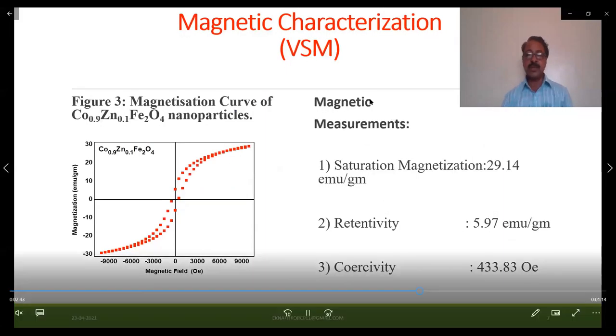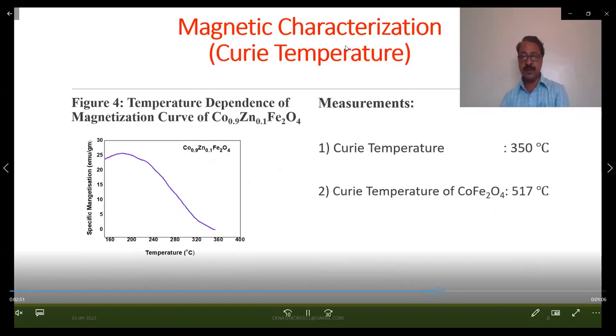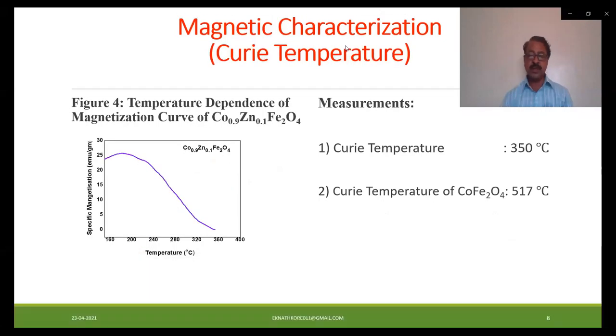The magnetic characterization done by VSM shows hysteresis due to cobalt content in the sample. These are the values of saturation magnetization, retentivity, and coercivity. Further magnetic characterization was done by a low magnetic field AC susceptometer. The Curie temperature was estimated by extrapolating the linear section of the curve, and it is 350 degrees Celsius.